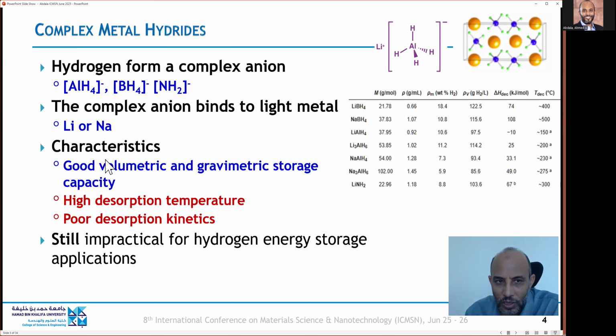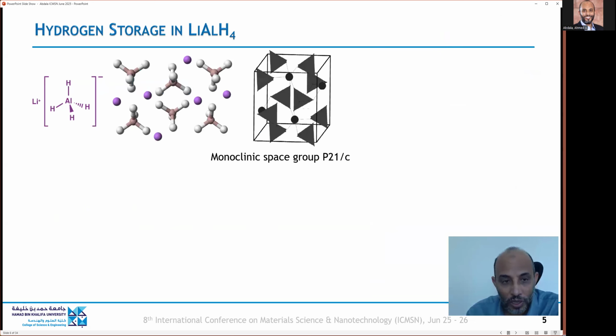So these complex metal hydrides provide good volumetric and gravimetric storage capacity, but they suffer basically from the high desorption temperature and also the poor desorption kinetics, as I indicated in the previous slide. So that's why they're still not used on a commercial scale. So we need to enhance both the desorption thermodynamics to reduce the desorption temperature, and improve the rate of desorption by enhancing the kinetics.